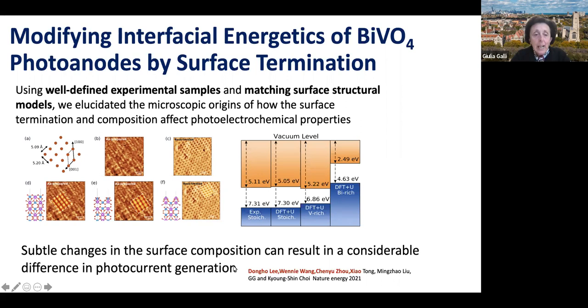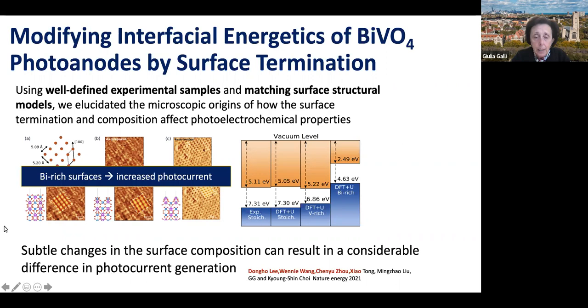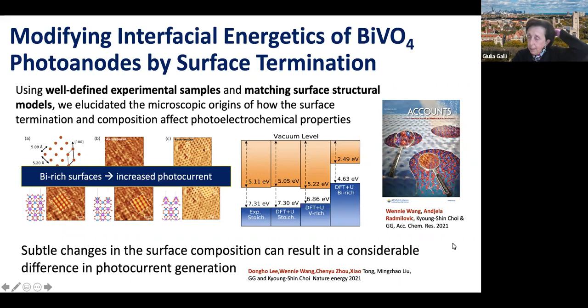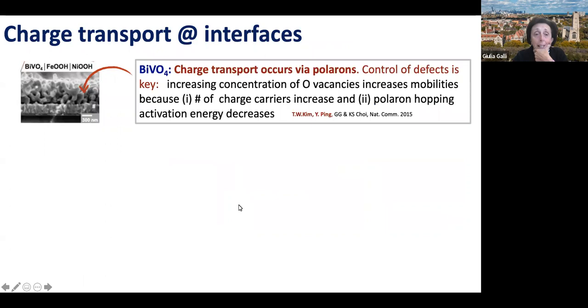And we found that very subtle changes in the surface composition can result in a considerable difference in photocurrent. And if there are experts in the audience, we determined that bismuth-rich surfaces increase the photocurrent. And in this work that just appeared last month with our experimental collaborator, we actually tried to explain all the back and forth and the procedure that we used to understand these surfaces and the integration of our work with experiment. All right, so once you know your surface, you want to know charge transport.